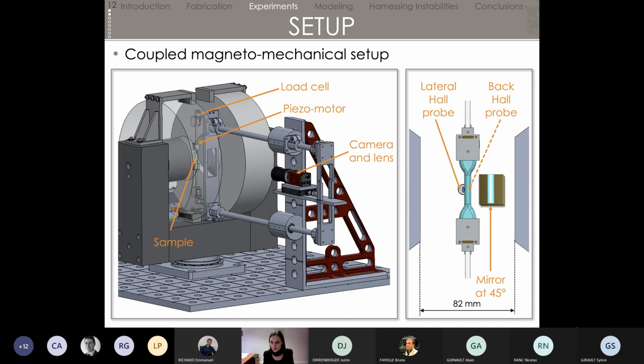So another view is here. You have also a mirror making a 45-degree angle next to the sample, so that when we look at our sample, we see the front of the sample, but also its side. And also we have Hall probes. So I'll explain what we measure with all that.